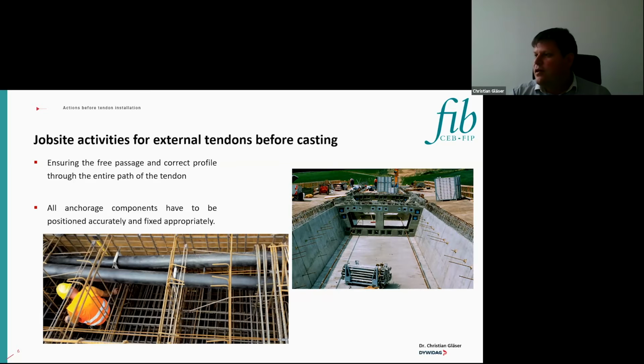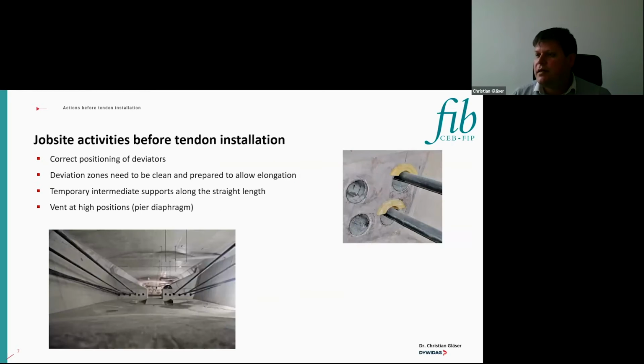So after the concrete is hardened, or once we are ready to install our external tendons, we have to take special care for a correct positioning of the deviators. So you see, for example, a solution with these half shell elements that needs to be exactly placed in the deviation pipes to enable a perfect deviation of the tendon. All deviation zones need to be clean and prepared to allow a proper elongation to avoid any damaging of the duct during the installation. Temporary intermediate supports along the straight lengths are required, and of course for grouting vents at high positions are required.